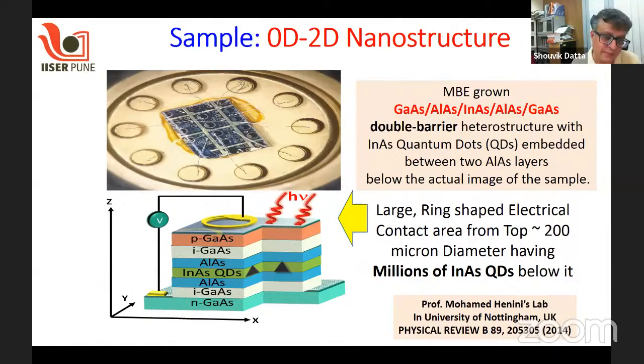So that was the background. Coming back to the sample, we are measuring molecular beam epitaxy grown double-barrier heterostructure samples, where within the two aluminum arsenide quantum barriers there are many millions of indium arsenide quantum dots. When I say that we measure capacitance, we measure between the bottom and the top contacts, which are quite large, with diameters of 200 to 400 micron, and below that there are millions of indium arsenide QDs. We use LCR meters and model our sample as a parallel combination of capacitance and conductance, and by these AC measurements we extract the capacitive component and the conductive component.